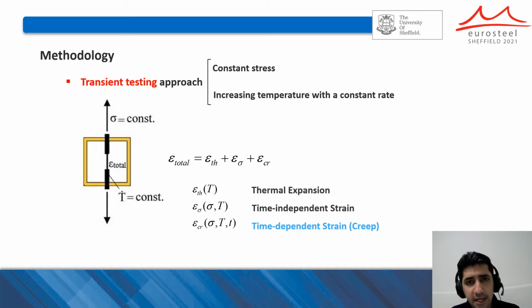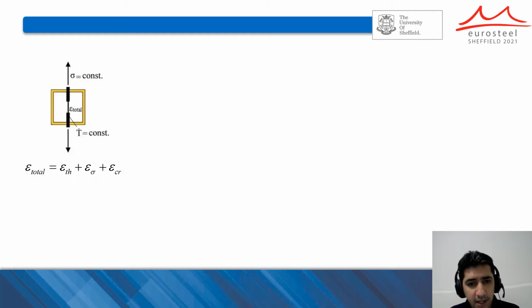The total strain itself consists of three components: thermal expansion, time-independent strain, and also creep strain, which is time-dependent. The thermal expansion component itself can be obtained individually if a load-free test is performed using a transient approach.